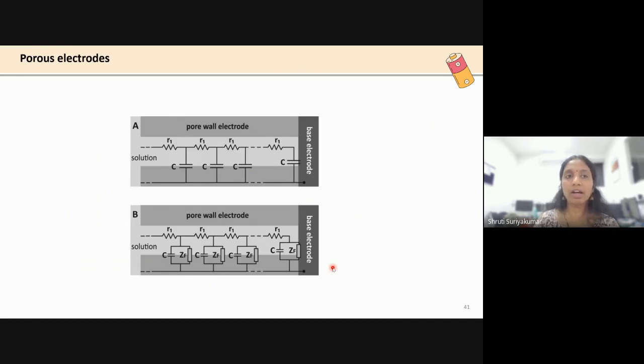So I am now coming to a few real-time systems. You have porous electrodes associated with the materials. And when you have a porous electrode, this is how your circuit is going to be. So you have R and C's in parallel. When you have a porous electrode wall, you call this a transmission line. A transmission line is a combination of R and C's arranged in this way. And because of the distribution within the bulk, your electrolyte has to go in and ion migration has to take place. Ions have to be accessed. So you will have a distributed RC, a distributed time constant, and you will have this as your equivalent circuit.